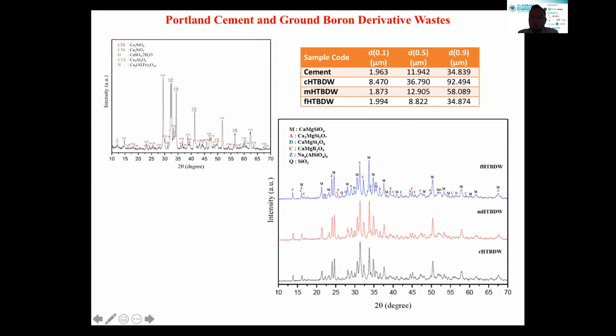So you are seeing now the XRD patterns of the ground powders. The XRD patterns are the same, with just a bit of difference here. The peak decreases with the decreasing of the particle size due to the amorphization of the phase detected by the XRD analysis, but all patterns are the same.